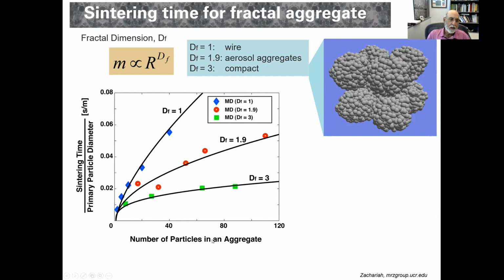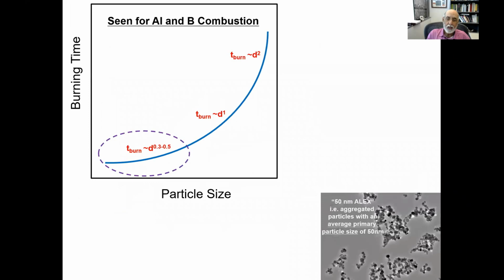What we've done here is we have shown that the time to coalesce divided by the primary particle size, this is this little object here relative to the whole object, as a function of the number of particles in an aggregate. So this has 1, 2, 3, 4, 5, 6, 7, 8 particles in this aggregate. As a function of number of particles in this aggregate, it really scales with the fractal dimension of the object. So this is molecular dynamics simulations. And these black lines are fits, and we can fit to one expression now. We can get the sintering time is proportional to the number of particles in the aggregate, effectively to the fractal dimension power. And then there's viscosity and surface tension in here and the particle diameter. This allows us to estimate sintering times.